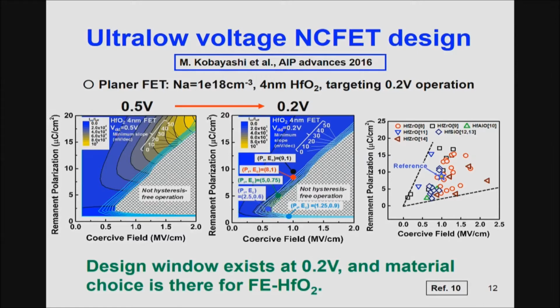If you look at the right figure, it summarizes a survey of experimental data of hafnium oxide ferroelectric capacitors. You can see that you can choose the appropriate parameters from the ferroelectric hafnium oxide material. So that's great. We can choose this material for low voltage operation.